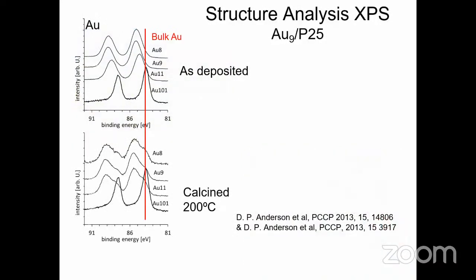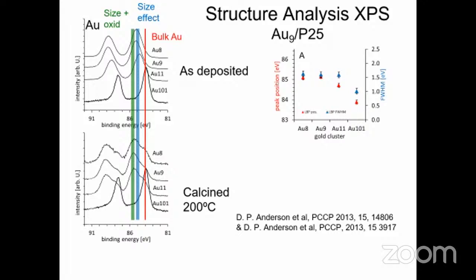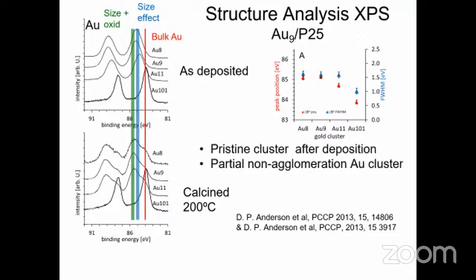We did a study on the synchrotron, and we show actually there is a huge difference between the gold 8 and 9 and even 11 and gold 101 atoms, depending on the peak. And this is what's called the size effect of the XPS. And this is related to the final state effect. What does the final state effect mean?